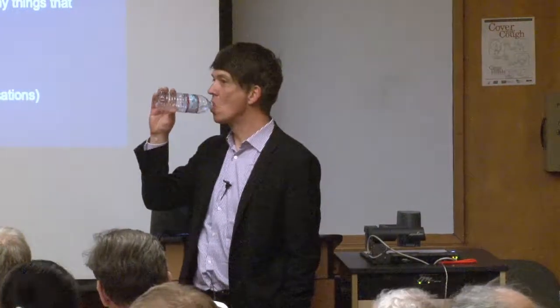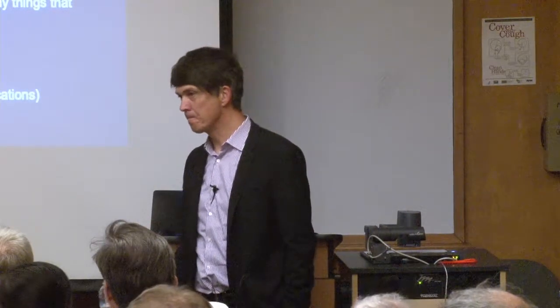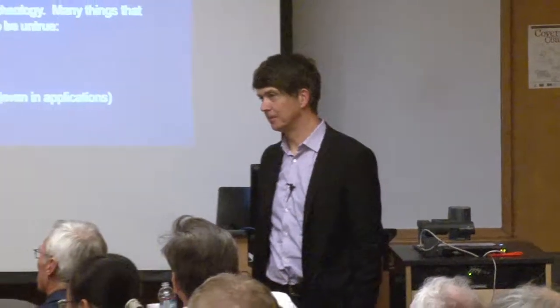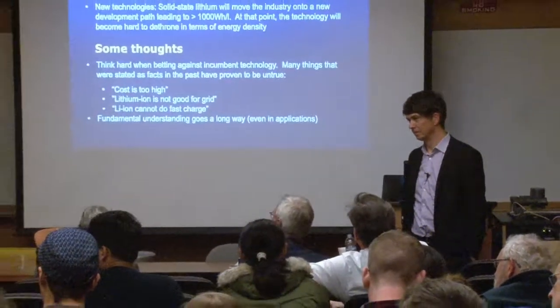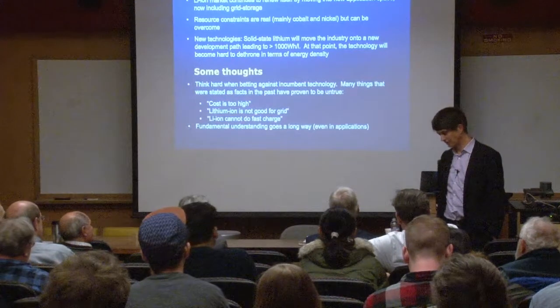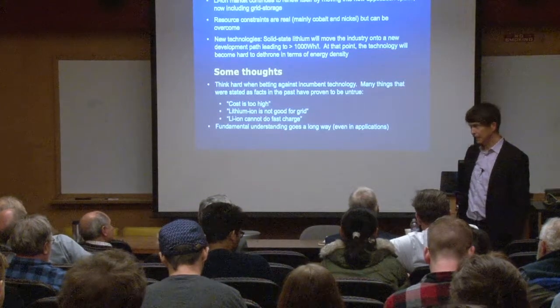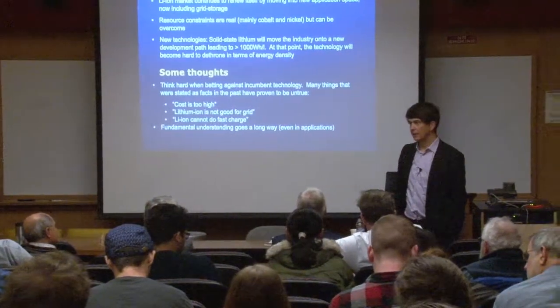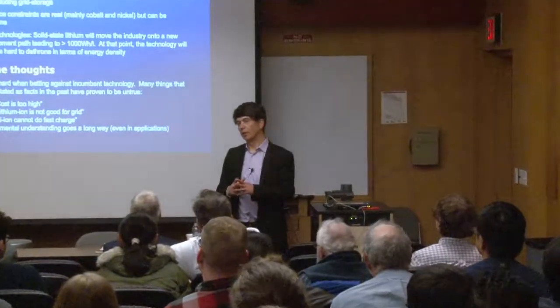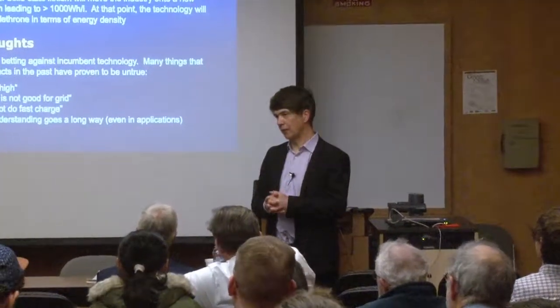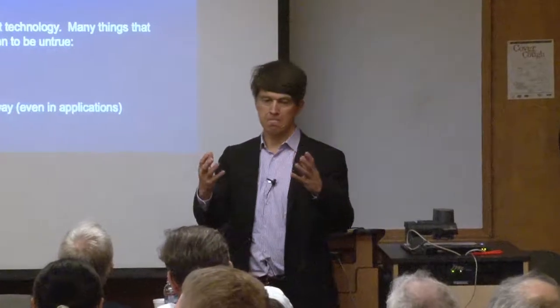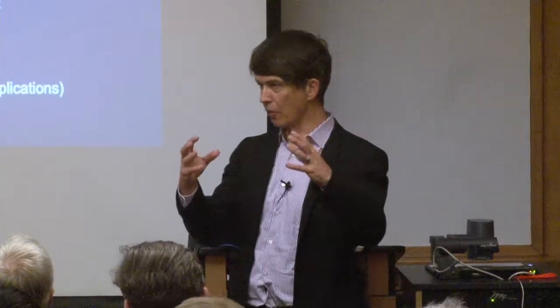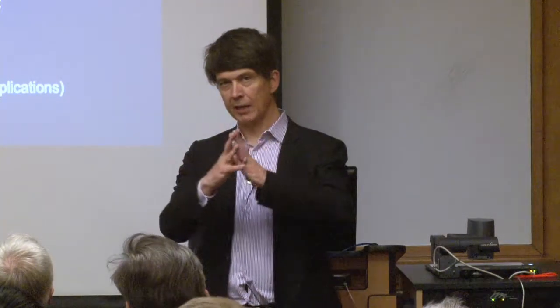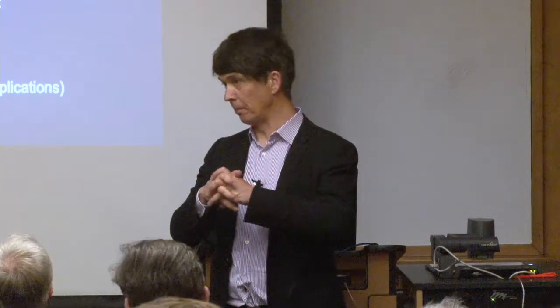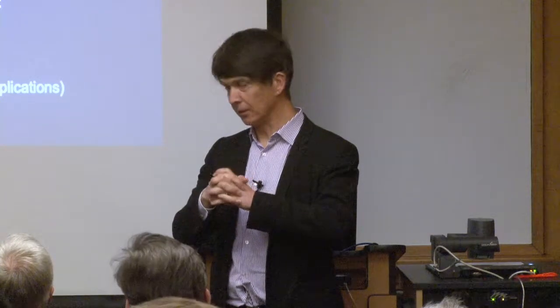I had a question on some of the challenges you raised, the mechanical issues, when you said there's cyclic expansion and then in the discharge you get contraction. What's the magnitude of the cyclic strains you talk about in those conditions that's going to last 1,000 cycles? So, typical volume expansion of a cathode: the cathodes are typically 5 micron to 20 micron agglomerates of particles, and they would expand anywhere between 5 and 10% in volume.